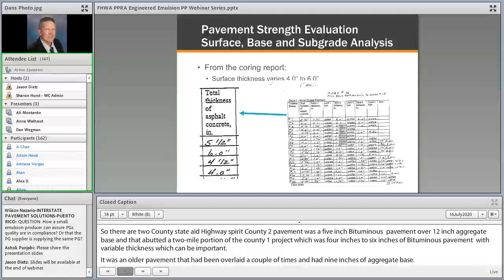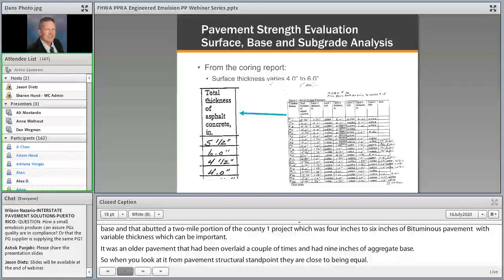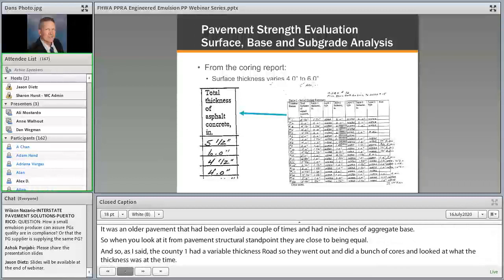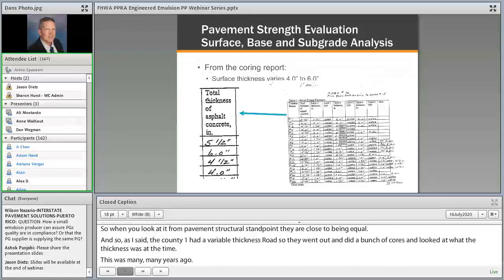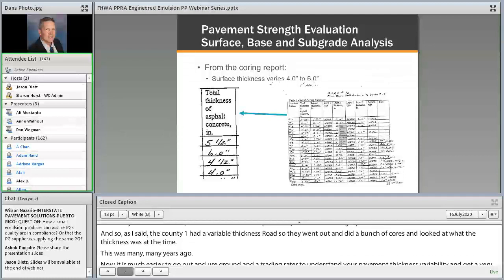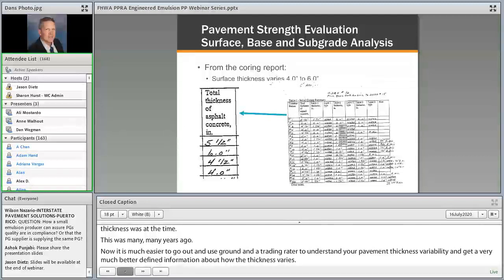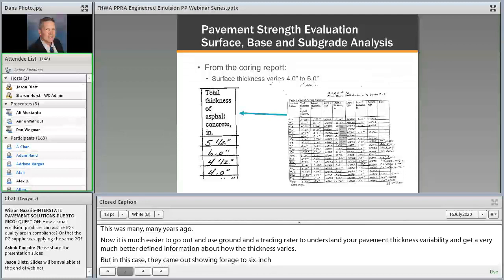And so, as I said, County 1 had a variable thickness road, and so they went out and did a bunch of cores and looked at what that thickness was at the time, and this is many, many years ago. Now it's much easier to use ground penetrating radar to understand your pavement thickness variability and get much better defined information of how that pavement thickness varies over the length of the project. But in this case, the cores came out showing that 4 to 6 inch thickness, and that fits with cold in place recycling in that typically you're looking at a 4-inch partial depth process where cold in place recycling is applied, and that allows the material to stand up to the equipment that's going to be used in that cold in place recycling process.